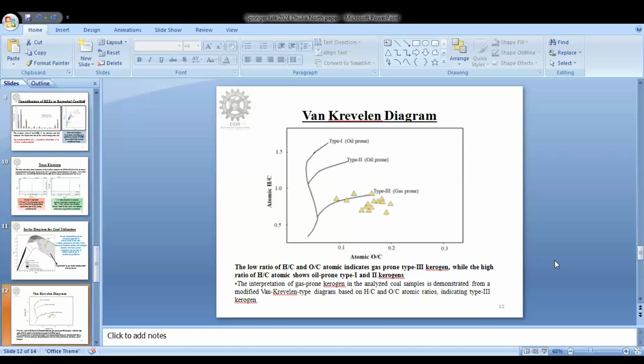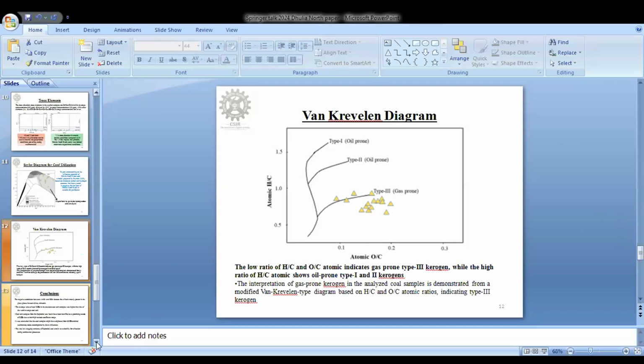And the last observation is the Van Krevelen diagram. This is again to know what kind of coal it is, which goes hand in hand with the previous graph. These coal samples from all the depths, as you can see, lie in type 3, which is basically the low ratio of hydrogen over carbon and oxygen over carbon. The y-axis is H over C, and this is oxygen over carbon. This indicates the gas prone type 3 kerogen, while the higher ratios, type 1 and type 2, are the oil prone coal samples. So in this case, we understood that these particular coal samples were gas prone and hence suitable for gasification. So these were the primary findings from the exploration based analysis that we did.